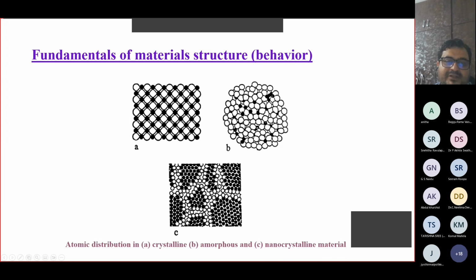And when you look at the nanocrystalline material where the grain size is less than about 100 nanometers, you see that the white ones are the ones which occupy the grain boundaries, and the filled circles are the ones which are part of the grain. Now you see that the volume fraction of the atoms that are sitting in the grain boundaries is comparable to the volume fraction of the atoms that are sitting within the grains. Therefore, these atoms also play a critical role in dictating the plastic deformation, whereas in conventional materials, the number of atoms that sit in the grain boundaries is way less, by several orders of magnitude, compared to the atoms that sit within the grains.